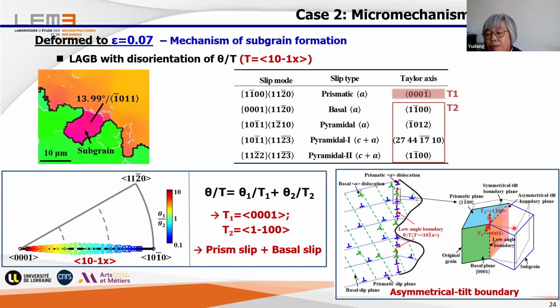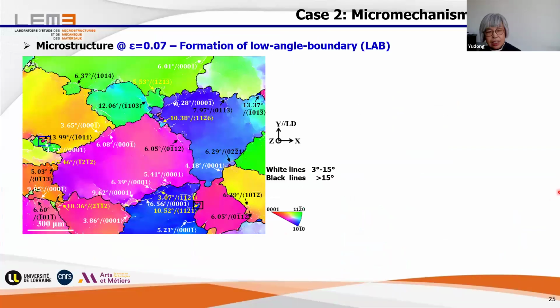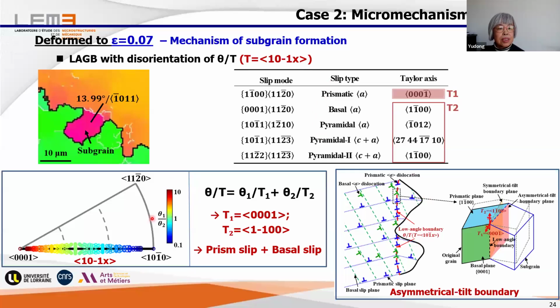And then we will have a new boundary with a larger angle. For this new boundary, you see, for the first slip we have a symmetrical tilt boundary, but by absorbing this basal slip dislocation, we will form this asymmetrical tilt boundary. And this allows us to well explain what happened to form such a boundary.